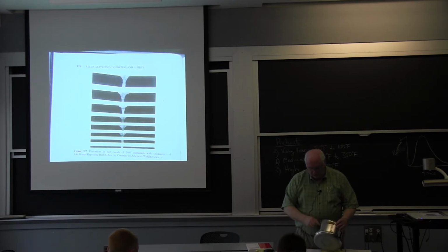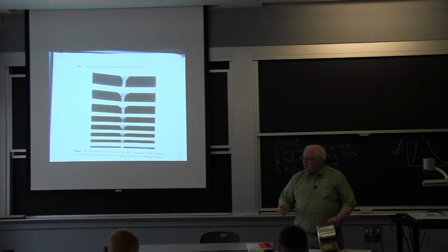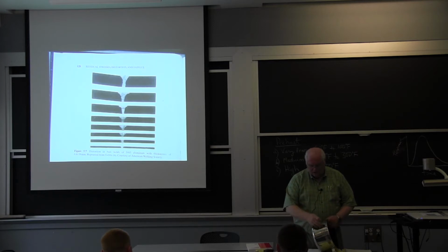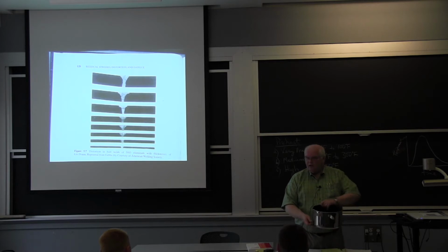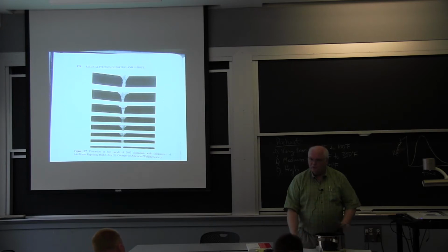But I noticed that the cracks were on the top, which was another clue. So it was delayed cracking. I mean, hydrogen cracking is called delayed cracking. I noticed they were at the top, and I know that when you take a flat plate of this type of steel and form it, you get the maximum deformation as you roll it up like this up here.